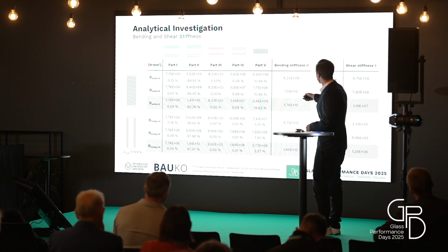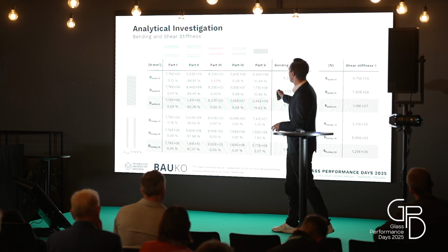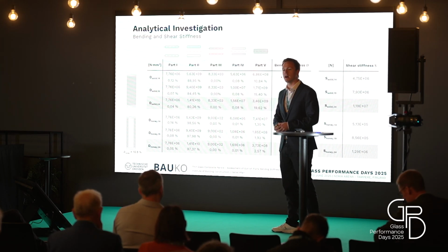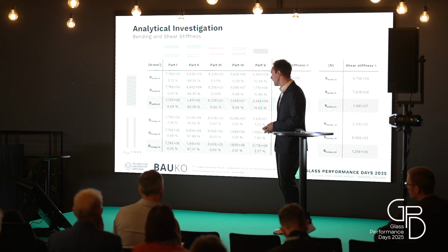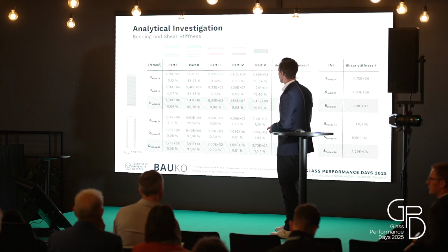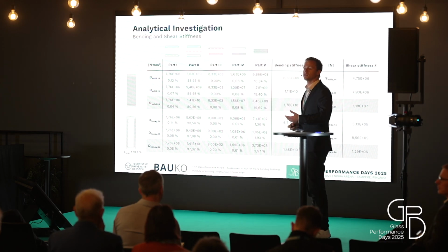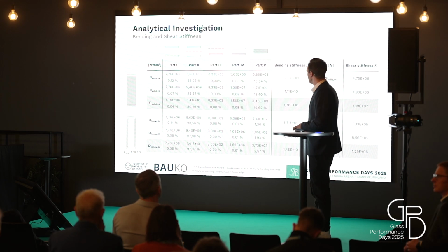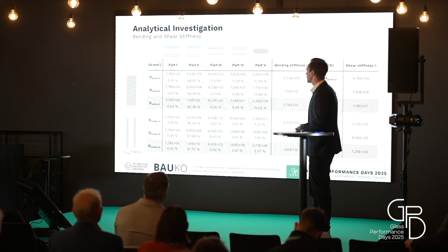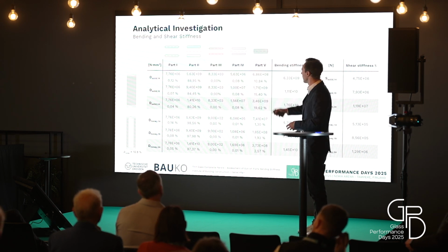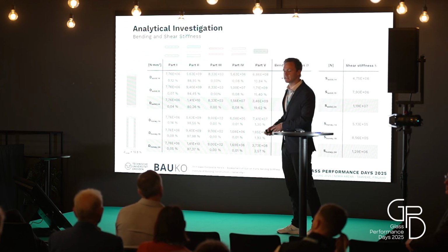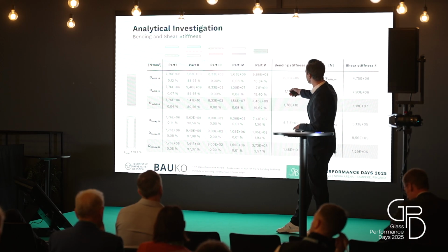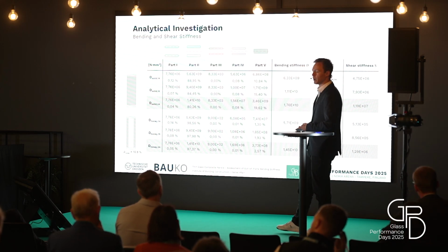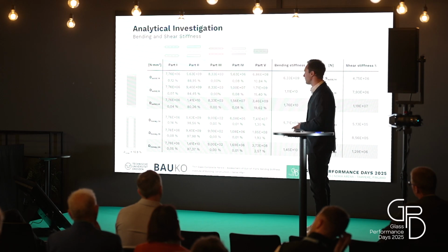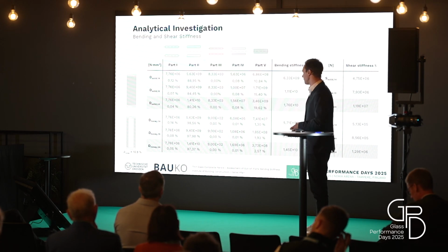And we have the total bending stiffness here in the very end, and we have these different parts, which I have already shown you before. And now it's quite interesting to look at the percentage of their contribution to the total bending stiffness. In that solid case, we can see that the major part is covered by the thin glass related to the central axis of the whole composite, but there's also a decent part for the bending stiffness of the core itself, around 10 to 20%, depending on the thickness of the core.